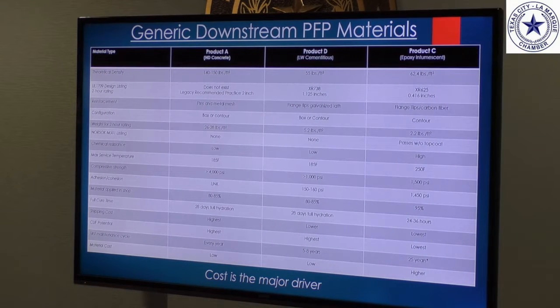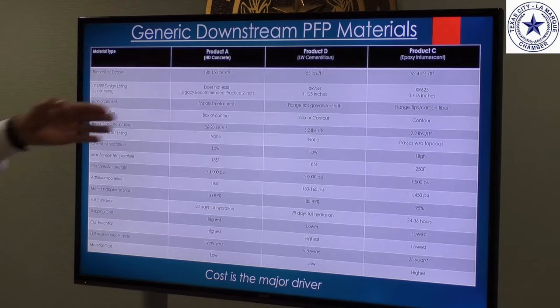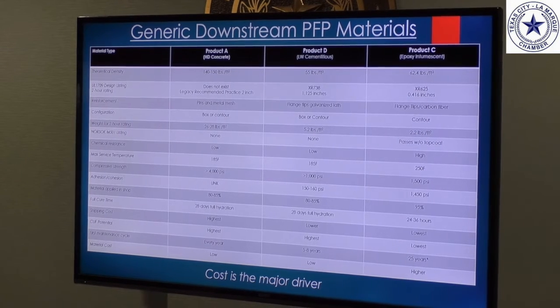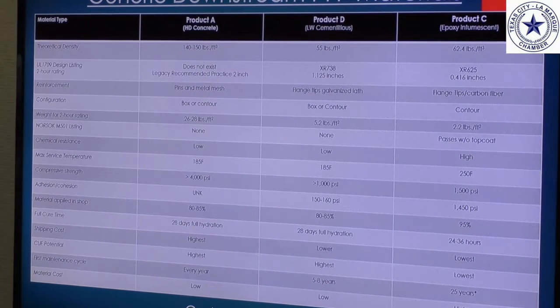For the purposes of this discussion, we're going to keep it generic. Product A will be high density concrete, product D will be lightweight cementitious, and product C will be your epoxy intumescent. The first thing to point out is, what's the UL 1709 listing and thickness of each product? High density concrete is a legacy product. It does not have a UL 1709 hydrocarbon pool fire listing. The old tried and true method in the plants is 2 inches of concrete gives you 2 hours of fire resistance. Product D, the lightweight cementitious, you need 1.125 inches thickness in order to achieve a 2-hour rating. Product C, you only need 0.416 inches in order to achieve a 2-hour rating.